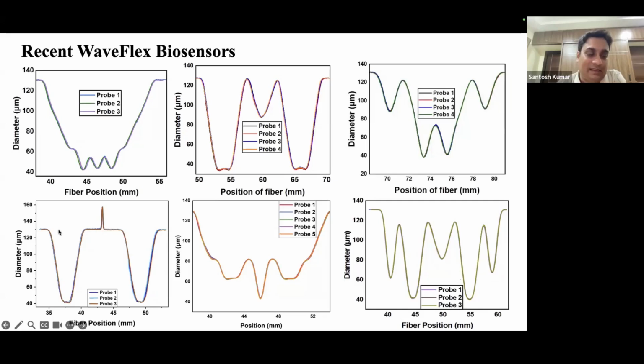So here we can see the original diameter was 125 micrometer, but what we did is we have taken two single mode fibers, and with the help of the fusion splicer machine we have just spliced them and made a bulge on the splice part. So we increased the diameter from 125 to 160 micrometer. Okay, and after that we have tapered it to 40 micrometer.